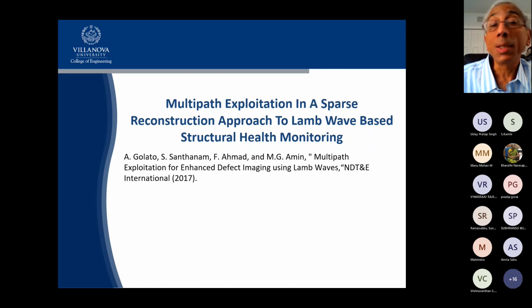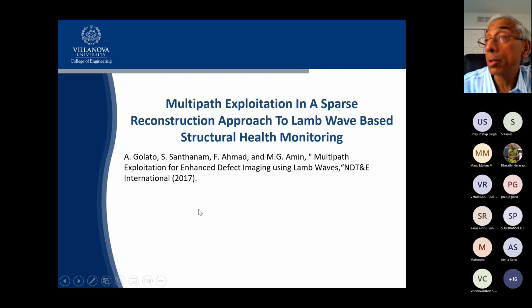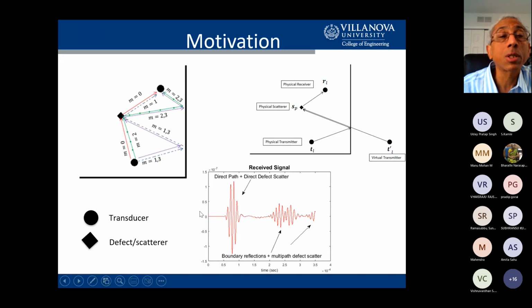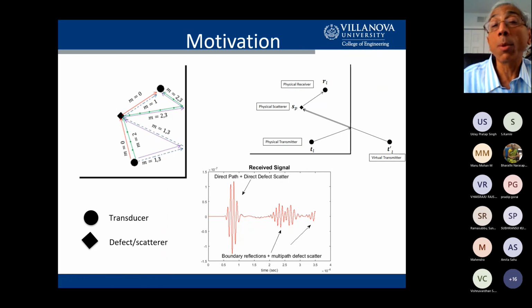I talked about the use of multi-path, which is, if you've got a plate with finite boundaries, you get a lot of reflections from the boundaries, and that can confuse the picture. But you can exploit that too. And so this next couple of slides will show you the concept of multi-path imaging. In this case, here's a transmitter, here's a receiver, here's a defect, and these two edges, one vertical, one horizontal, represent the edges of the plate. You could have a wave starting from your transmitter, hitting your defect, and then coming to your receiver. The same wave that emanates from your transmitter could hit the wall, bounce back, hit your defect, and then arrive at your receiver. So there are multiple pathways for a wave to start at the transmitter and arrive at the receiver, interacting with the defect and with the edges of the plate. So how do you exploit all that information?